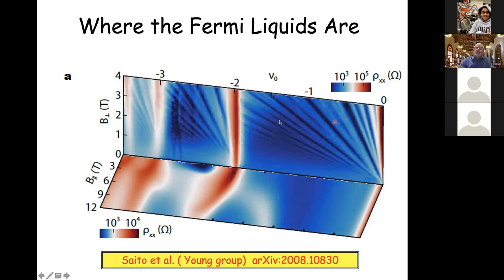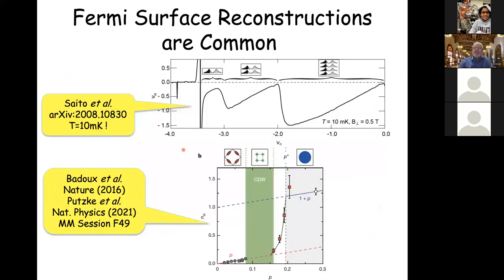If I start to remove electrons, I can get close to band filling -2, and I'm in a Fermi liquid state. And if you look closely at these Shubnikov-de Haas oscillations, it tells you that 2 of the 4 flavors have their valence bands completely empty. And in this region, I have a Fermi surface in the 2 remaining flavors that are gradually being emptied. And this is where the superconductivity occurs. This picture of Fermi surface reconstruction is verified by weak field Hall measurements.